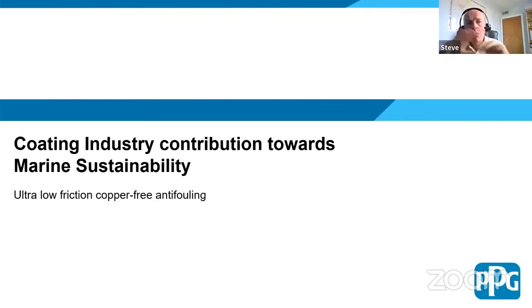Now, not everybody is in a position to adopt fouling release coating technology for various reasons. It could be budgetary, it could be operational, it could be something else altogether. But we still try and achieve as good a performance as possible with a conventional antifouling. And here we're looking at an ultra-low friction copper-free material. This is a biocide-based coating. So this is not a fouling release coating. This is a biocide-based coating, but it is copper-free.